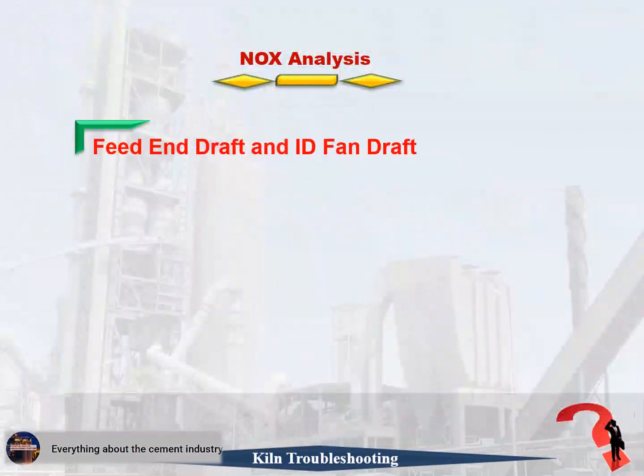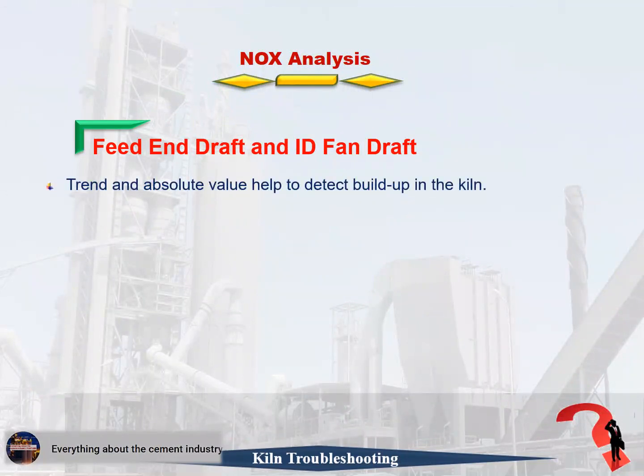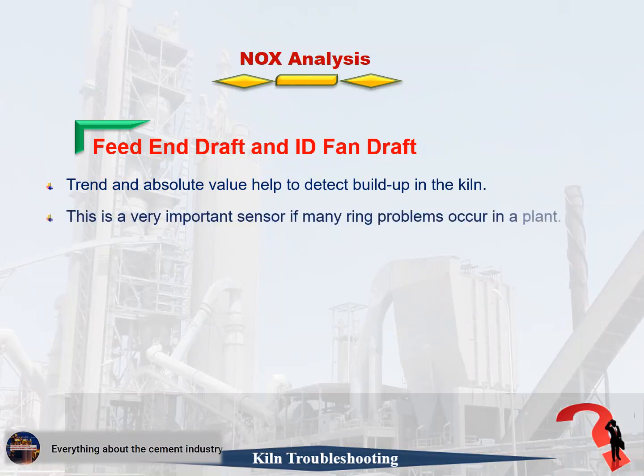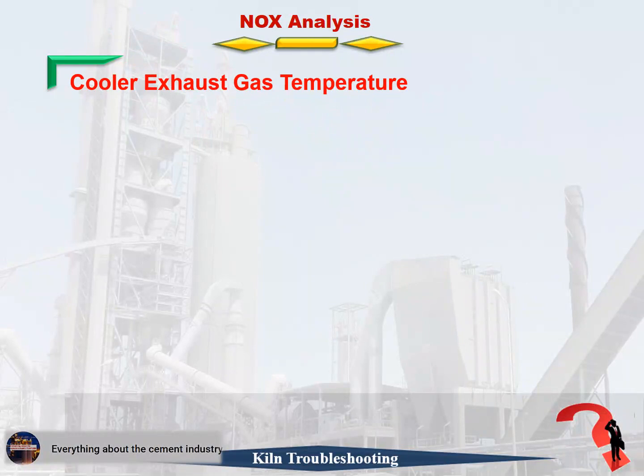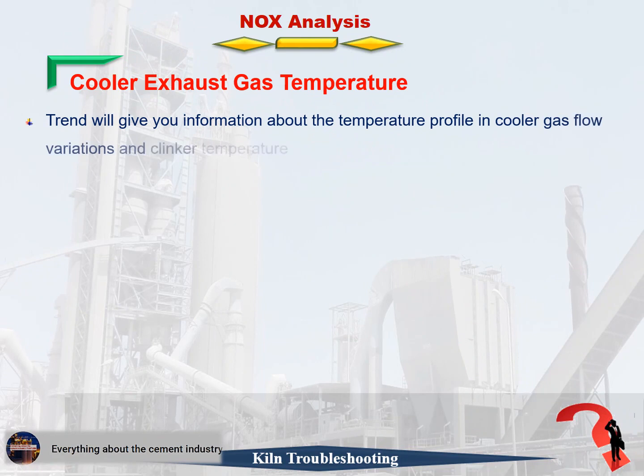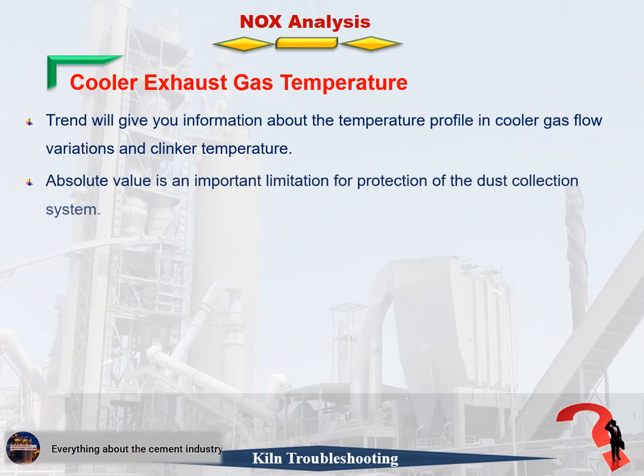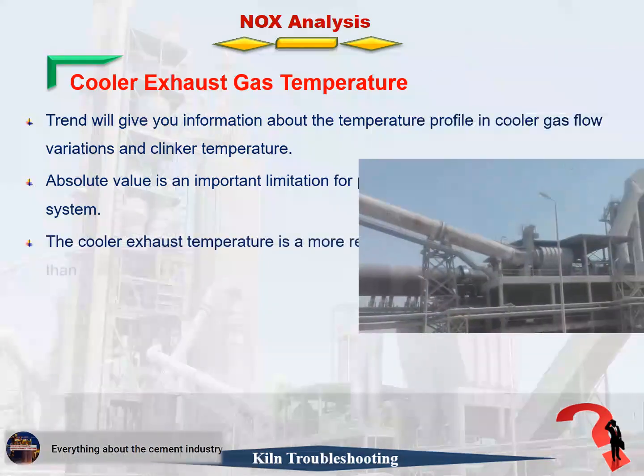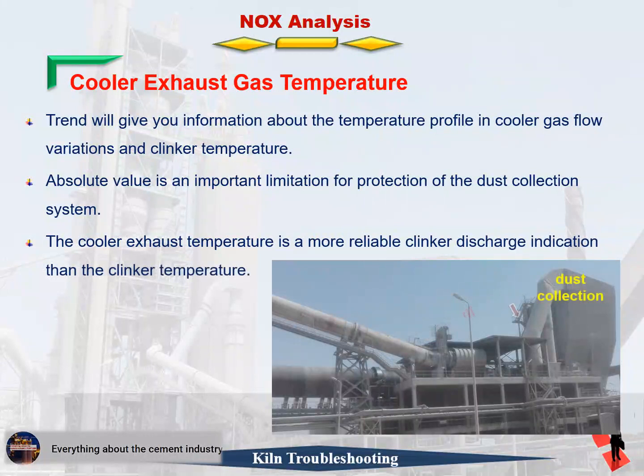Feed end draft and ID fan draft. Trend and absolute value help to detect build-up in the kiln. This is a very important sensor if many ring problems occur in a plant. Cooler exhaust gas temperature. Trend will give you information about the temperature profile in the cooler, gas flow variations and clinker temperature. Absolute value is an important limitation for protection of the dust collection system. The cooler exhaust temperature is a more reliable clinker discharge indication than the clinker temperature.